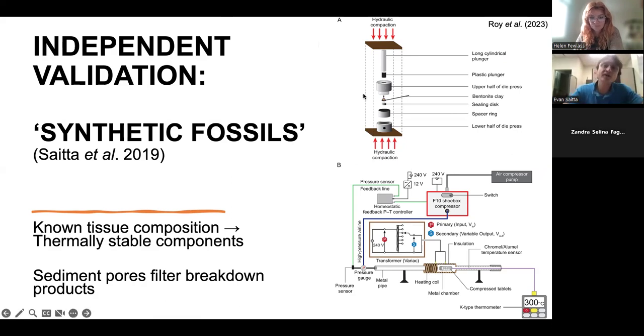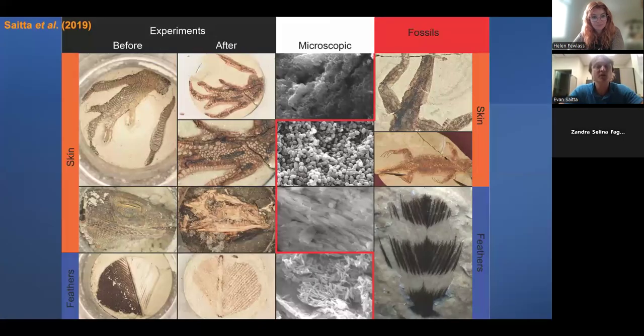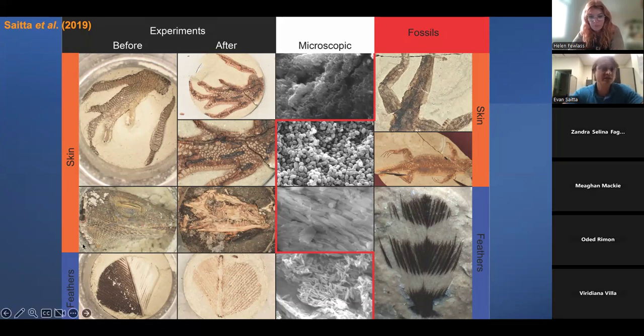And the compaction within the sediment that we do acts as a filter. And so it allows you to trap the thermally stable components and then allows for the escape and the leaching away of unstable components, kind of like what we were talking about with bone, where broken down proteins can leach away. And we have a lot of success with some of these experiments. So you can take bits of lizards and feathers, and you can expose it to sediment encased maturation. You get brown bones, you get these brown stains around the bones, you get loss of volume, loss of proteinaceous tissue like muscle, loss of fats, loss of connective tissues, collagenous connective tissue.